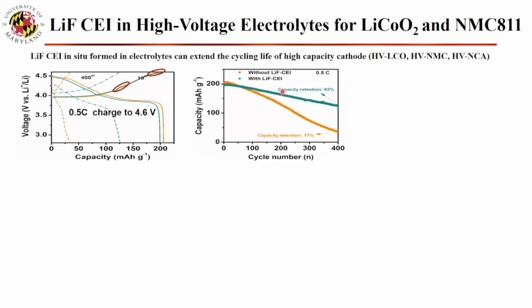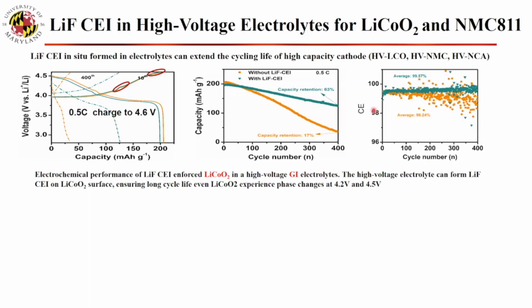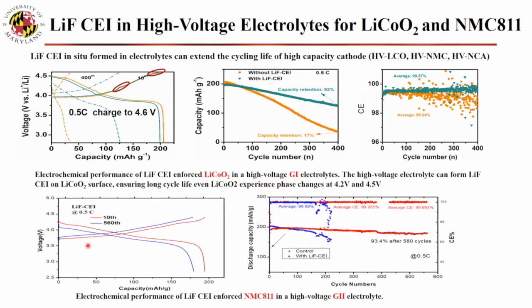If we use our high voltage electrolytes, they can form a lithium fluoride. They're much more stable than the traditional electrolytes. Coulombic efficiency can reach 99.5. So this is generation one, high voltage electrolytes. So we have a generation two electrolyte. We tested it in the NMC811, and this is the cycle life. So it's 500 cycles. Coulombic efficiency, 99.99, same as graphite, really stable.